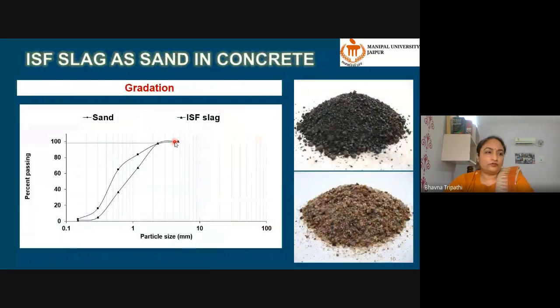The gradation of ISF slag. So ISF slag, as I said, resembles natural sand very closely. This is the picture of natural sand, and visually there is no difference except for color. However, when we conduct the gradation or particle size analysis, there is a slight difference in a few of the sieves, and we can say that ISF slag conforms to zone 1. It is coarser, and particularly the difference lies here.